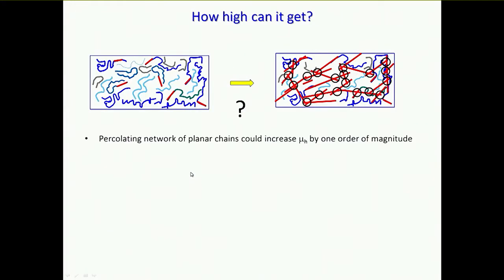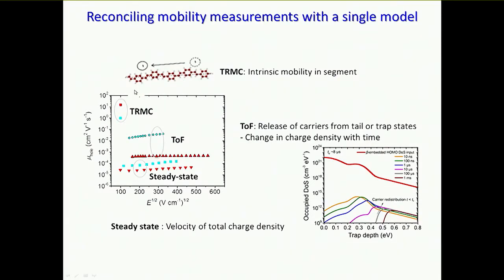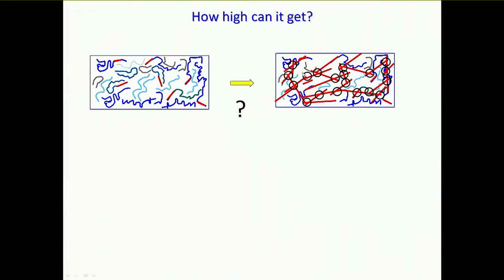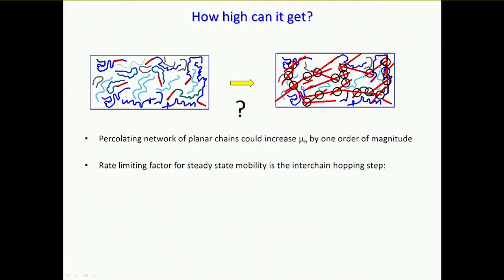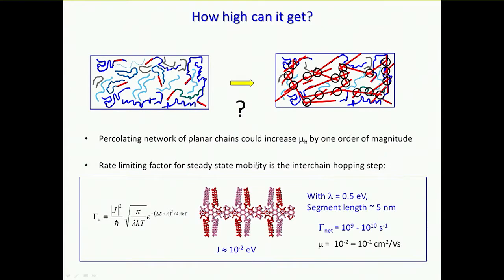So that then led us to an interesting question, which is how high might the mobility get? So we think from these time-resolved microwave conductivity measurements, and also ones that have been done very recently on a more planar polymer, an indacenodithiophene benzothiadiazole copolymer, we have an idea how fast transport can be along the chains, and we think it can be fast enough to make the rate limiting step the jumps between the chains. So if we take that as a possibility, and then consider the rate of the interchain hopping step, this is for the case of the polymer I just mentioned, the IDT-BT polymer, we consider the strongest coupling between chains, we can make an estimate of how fast the mobility could possibly be.